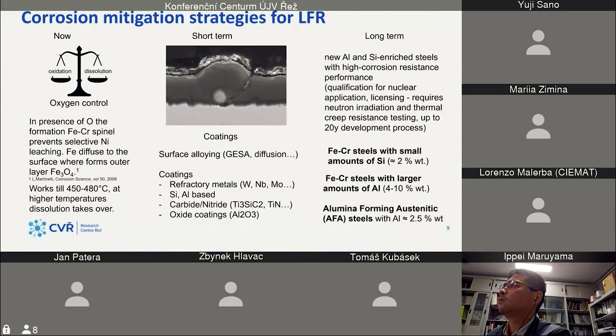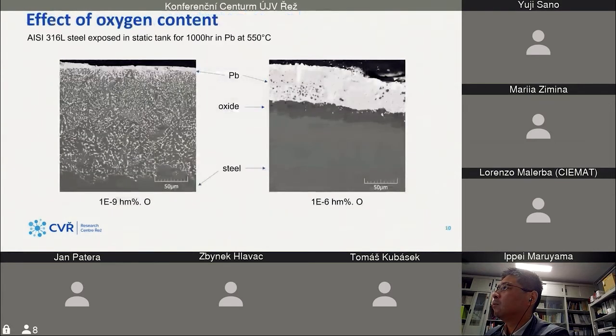In the long term, we can develop some aluminum or silicon enriched steels that have high corrosion resistance up to like 600, 700, even more degrees C, but it's a long-term process with all the qualification and irradiation. It's estimated to take something like 20 years. Therefore, for ALFRED, we plan this oxygen control method with possibly some coatings.